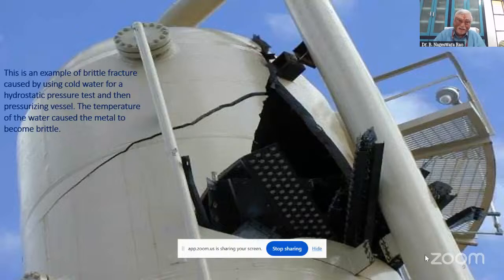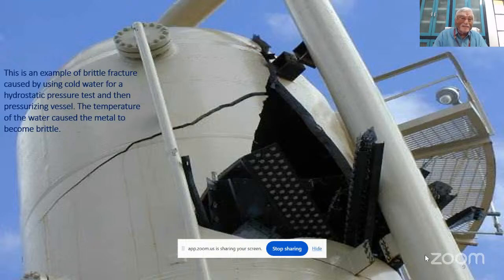Another one is a brittle fracture. How was it caused? The structure was designed with room temperature water, but it was loaded with cool water. As you know, when it is below room temperature, the material will become brittle and initiate cracks. It is not just because of the load, but because of the environmental effect, the strength is degraded. When you apply a small amount of load pressure, it creates the fracture and fails.